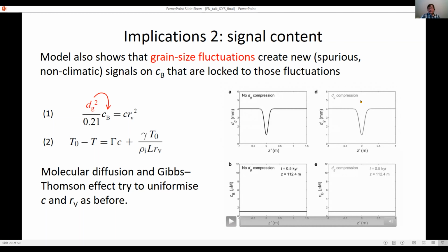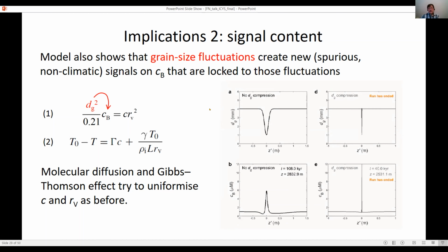In this, we let it compress with layer thinning. And then we couple this to the equation that I showed you. What we find is that these grain size fluctuations drive the spontaneous evolution of signals locked to them, not migrating. But these signals are non-climatic in the sense that they didn't come directly from the deposition. So one issue may be that recrystallization processes can generate short grain size fluctuations in the ice cores. We know there are lots of fluctuations in grain size. And then these spurious non-climatic signals could further corrupt our records. This is just a theory. We need to do more with this, comparing observations, maybe with grain size profiles.